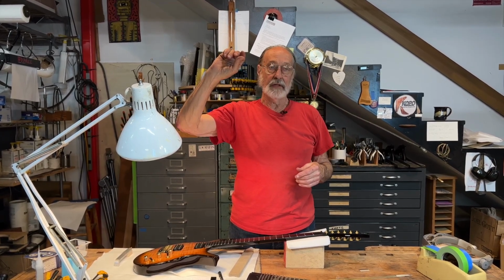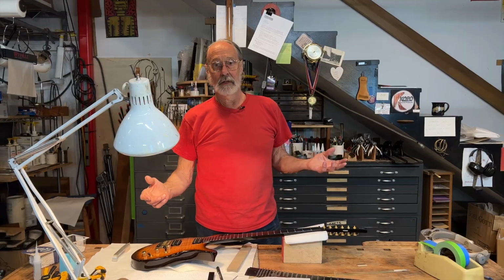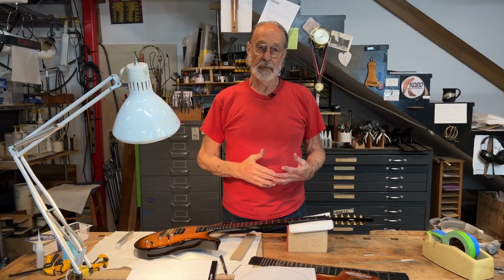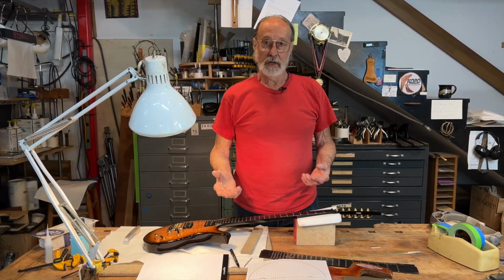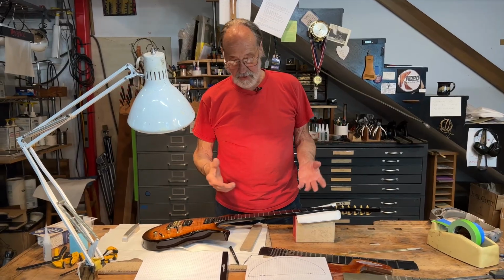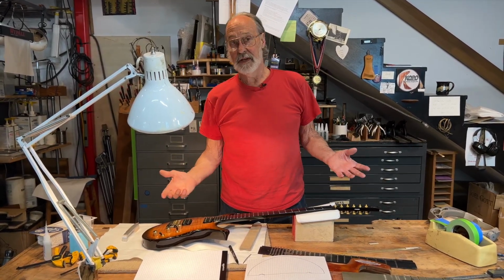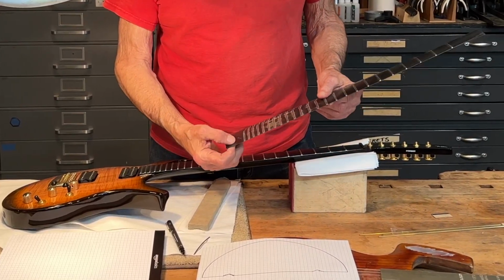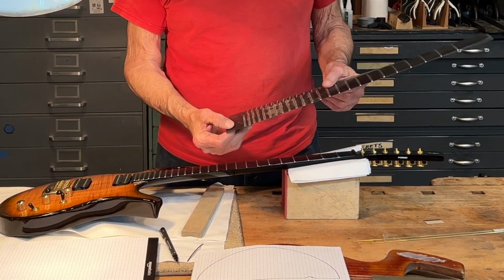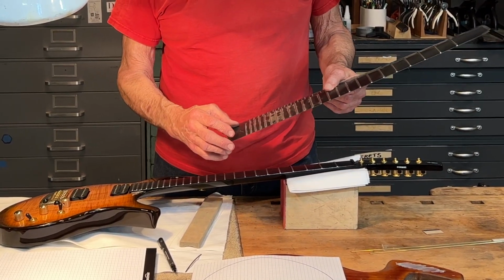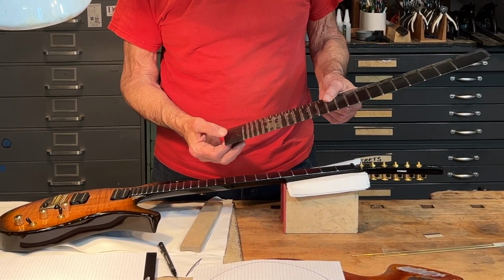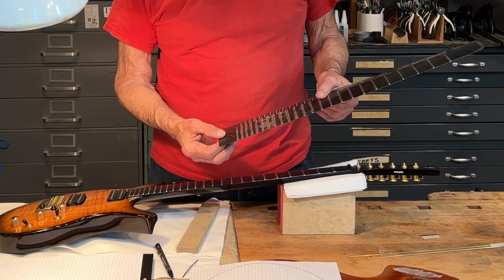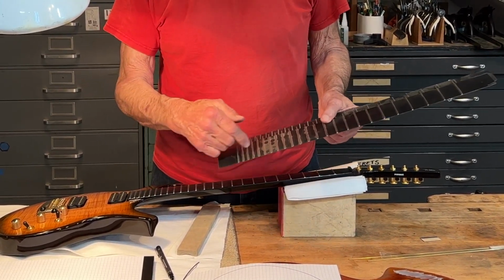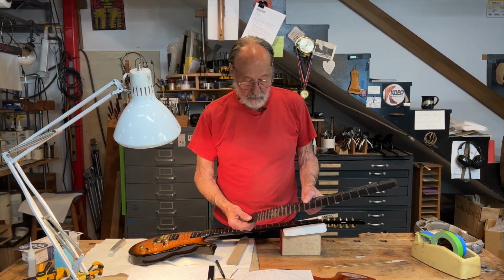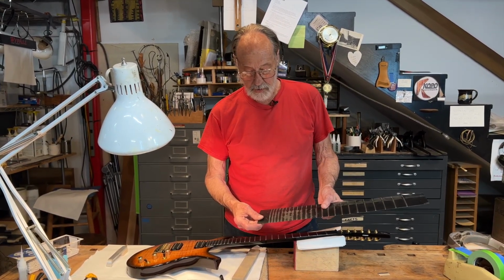And then the third way of doing it was with a chemical activator. So, another group of chemicals that would initiate the polymerization of this acrylic adhesive and create a good bond. Obviously we used the activator method because it wasn't okay to get this material too hot. The temperature that this acrylic adhesive cured at was too hot for this material to tolerate. And obviously you can't get light in because everything's opaque. So we used an accelerator to cure the glue.